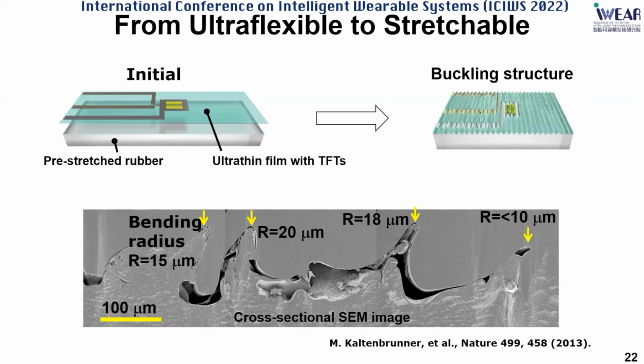After manufacturing of organic devices on 1 micron thick substrate, we prepare the pre-stretching rubber and laminate the devices together. And after relaxation of pre-stretching, the rubber starts shrinking, yet the plastic foil doesn't shrink at all. So in that way, the buckling structure can be easily formed. So when we look at the cross-section by SEM, you may see the buckling structure can be nicely formed.